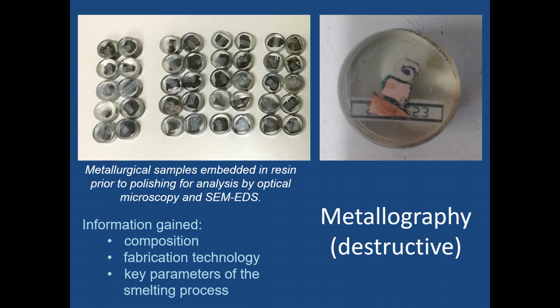And in this case, we're using the technique of metallography, which involves, as you can see here, mounting small pieces of these samples in epoxy resin and polishing them smooth. And then we look at them under a microscope, and this can tell us about their composition, their technology, and key parameters of some of the smelting processes that we see at the site. I'll just talk through some of that now.